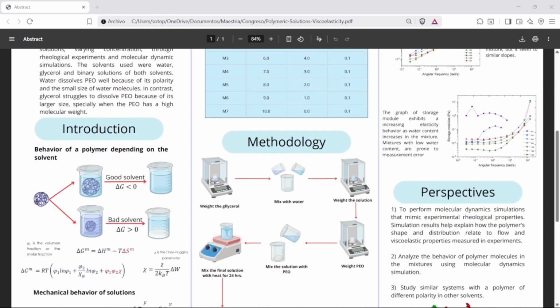The behavior of a polymer in solution varies depending on the solvent selected. The way the polymer folds is directly affected. In a good solvent, the polymer will exhibit stronger intermolecular interactions rather than intramolecular ones, resulting in minimal folding. Conversely, in a poor solvent, the polymer tends to favor intramolecular interactions over intermolecular ones, leading to increased folding and even potential precipitation of the polymer from the solution.